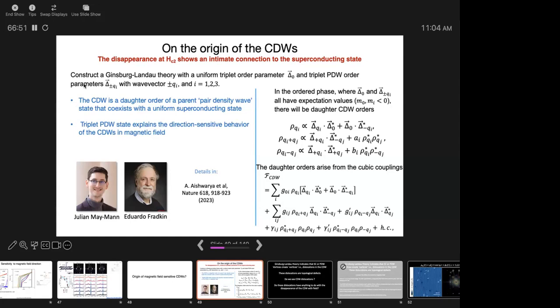So the first time we did it, we went to 1.6, 4, and 10. We saw it gone at 10. We saw it was there at 4. But we did experiments last month, and we know now it goes away. You can't believe this at 4.8 Kelvin. How could it be a daughter that survives in the absence of superconductivity? Yeah, so I have asked Eduardo and Julian this question, and they assure me that there are scenarios where you can have a charge density wave state that persists to a few degrees above TC, even if it is a daughter order of a PDW. They explain how that is possible.